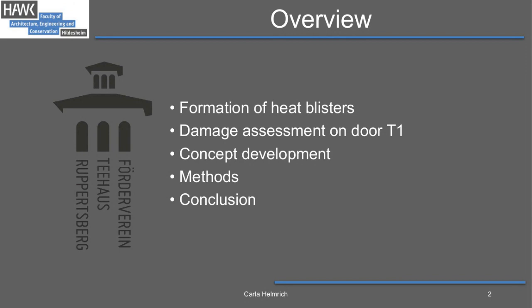Before I dive right into my work, I would like to briefly introduce the term heat blisters. Typical damage phenomena caused by extreme heat can be expressed in the form of changes in color or of the varnish, heavy soot formation on the surface, or blistering. For the latter type of damage, the term fire blisters is often used, but the term fire blisters reduces the cause of blistering to the effect of fire and the associated heat. However, other tools such as a lamp, for example, that is too hot, or an improperly used heating spatula can also be responsible for the formation of blisters. For this reason, this damage phenomenon can also be referred to as heat blisters, as it is ultimately caused by extreme heat input. Thus, the terms heat blisters and heat damage are used in this context. All right, after establishing these terms, we can start.